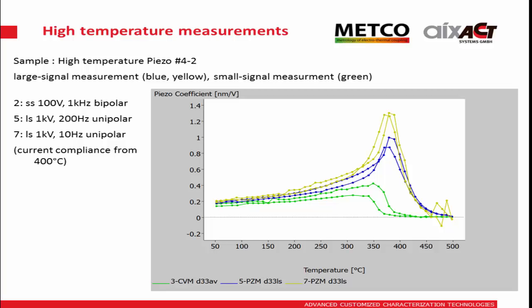I think Paul, you will explain the process to explain the behavior, but this also shows that it's very different whether you do resonance analysis or apply large signal, for example, if you want to use the materials for actuation at high temperatures. So that means both kinds of characterizations are needed. And maybe to mention that at the high temperature here, it runs into current compliance, so the drop could be even less pronounced if we drive more power into the sample.